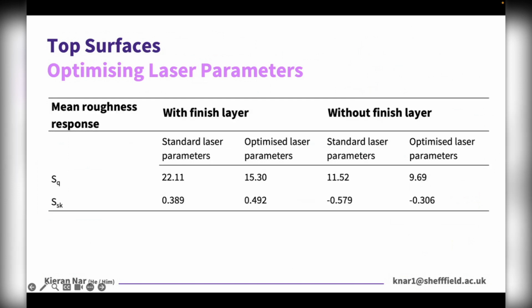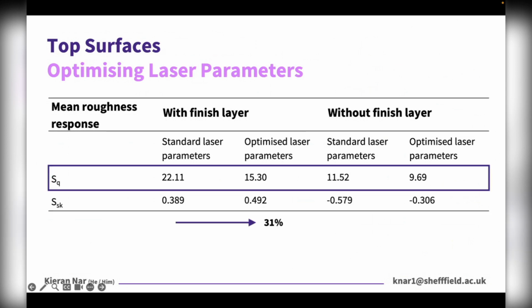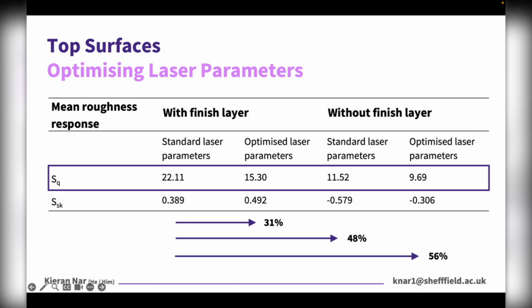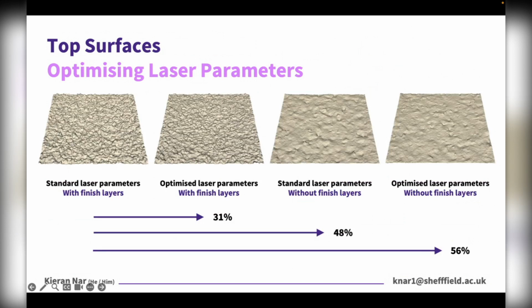And ultimately, we found that employing optimized laser parameters, we were able to reduce SQ roughness by 31%. Though to put this into perspective, when we instead build without finish layers, we managed to get reductions in SQ roughness of up to 48%. And finally, when we combine both of these mechanisms, so employ optimized laser parameters and build without finish layers, we found that it was possible to get reductions in top surface SQ roughness of up to 56%. And these scan images show the same findings, but visually, which I think highlights the magnitudes of these reductions really nicely.